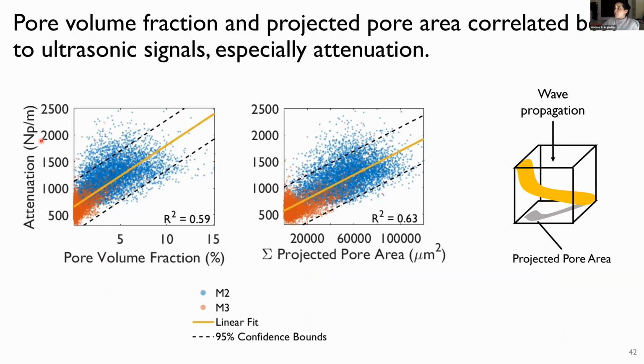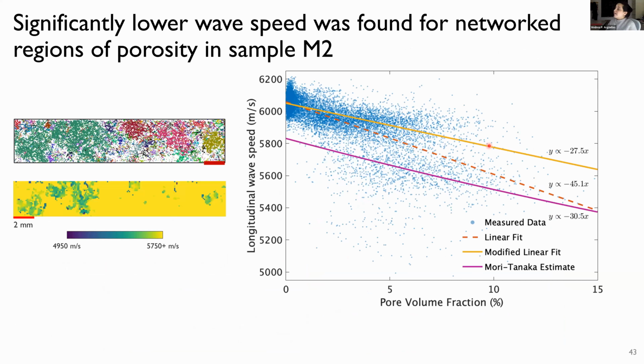So in doing that, we did point-to-point correlations, and we saw that both the pore volume fraction, as expected, but also that some of the projected pore area showed pretty decent correlations on a point-by-point basis to the attenuation measurements, which was really good to see, as it could give us some quantitative information about what was happening in these samples. Now, I think some of the more interesting results are actually on the wave speed side.